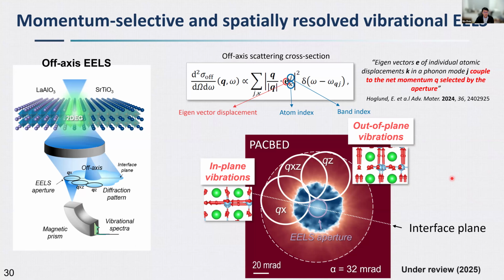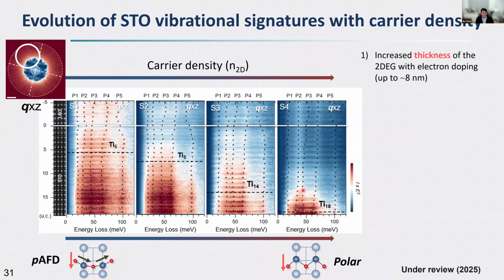And the last point, the missing puzzle, is to look at the phonon modes. I'm not getting into the details here, but basically we can shift the diffraction pattern to make the electrons getting into our EELS aperture with momentum either parallel to the interface or perpendicular to the interface. And we can also shift it 45 degrees to collect both in-plane and out-of-plane vibrational modes. So we're just looking at the results. The first scenario is when we use a QXZ geometry, we collect both in-plane and out-of-plane vibrational modes.